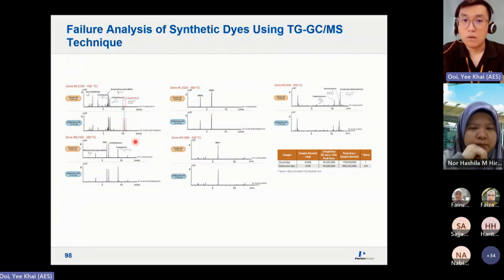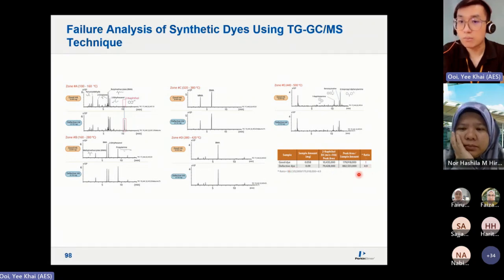Then from here, we extract it and match with the MS libraries. We identify it as 2-naphthol, based on the mass-to-charge ratio of 144 at this particular retention time. And then based on the peak area, we can do a ratio. So you can see that the defective dye has 5 times more of the 2-naphthol additive compared to the good dye, hence causing it to have a failure performance.